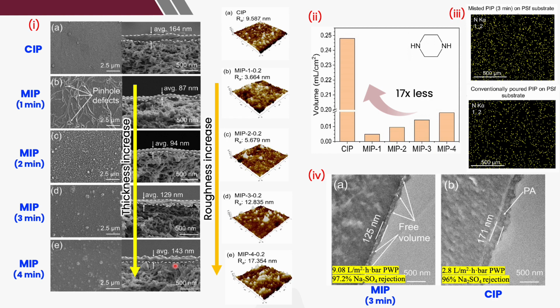However, we found that when you have too much monomer on the membrane surface through the misting process, these small water droplets will form larger water droplets on the membrane surface before you introduce the second monomer, and this actually causes a lot of pinholes on the membrane surface, which is not good for rejection. So what I want to highlight here is, if you look at this data, the MIP3, which is considered our best membrane, requires less than 17 times chemical to form a polyamide layer.